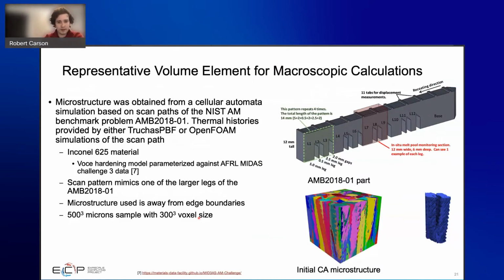Back in 2020, we ran a set of studies where we used similar scan patterns from the NIST AM Bench problem, which is the problem that we're trying to simulate within the ExaAM project. We generated a microstructure using ExaCA, which is our cellular automata code, which is also open source, I'll mention. And then we ran a fairly large sample that's about 500 micron cubes. We made it very well resolved with roughly 27 million elements within this cube.